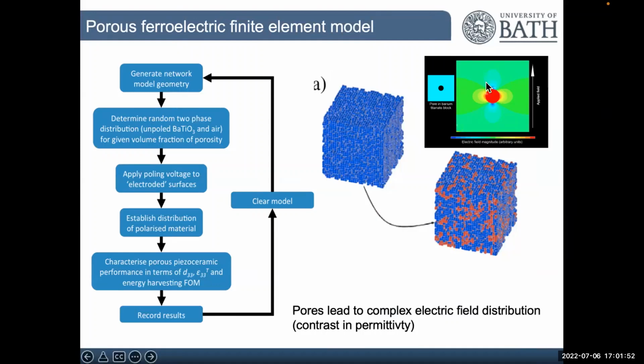And the pores produce some complexities in terms of that poling process, because the electric field will focus in and be concentrated in the pores because it's a lower permittivity phase compared to the ceramic. So the ceramic will have a relative permittivity of 2,000-3,000. Air is 1, and so the electric field will be within the pores. You have to design the appropriate microstructure to mitigate against that.